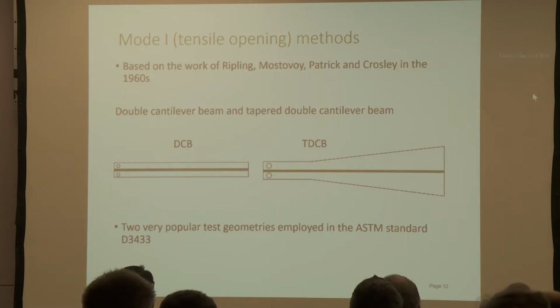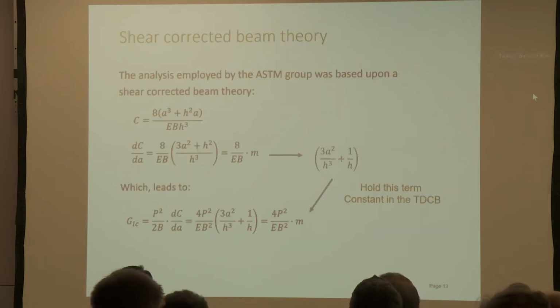D3433. And the analysis employed was based upon shear-corrected beam theory, where the compliance took into account the contributions of bending and shear, and then, of course, the compliance is differentiated into the Irwin-Kies equation, and the equation for G1C could be fitted in this way.